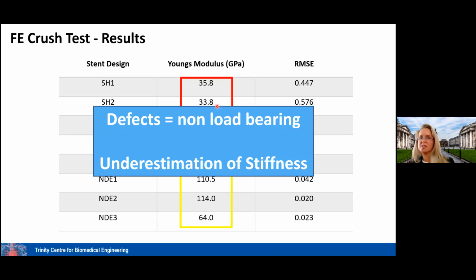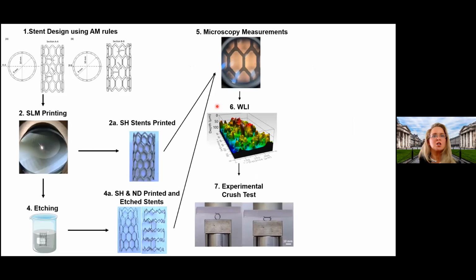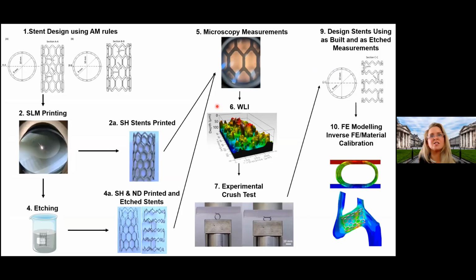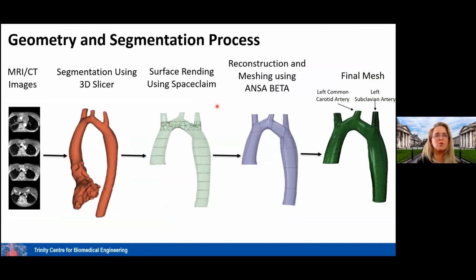So defects, these non-load-bearing defects, can result in that underestimation of the stiffness of the stent, and this could have big implications when designing stents, so it's another reason to make sure to post-process this through etching. So finally, once we had done this inverse FE to calculate the stiffness of the stent, we were in a position that we could actually use our geometries that we obtained clinically to create stents for a particular application, or bespoke stents. So how do we go about that?